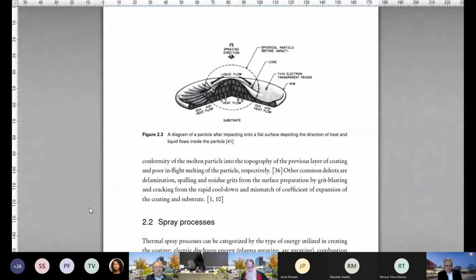So the roughness magnified of a surface would be something of this sort, and we measure the roughness based on the peaks and valleys. If the splat is too big or the roughness is too small, the splat would basically end up staying on top, and the consequent splats would come on top of it to form the coating. But this is not a good adhesion for the coating, and it's also not good heat conduction to the substrate. So there are these two factors.